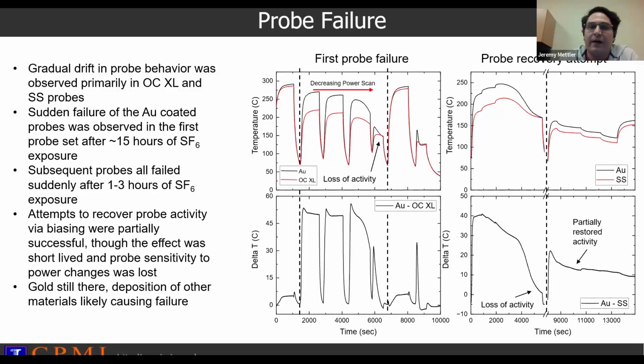Some bad news is that, unfortunately, the environment is quite punishing, and after some time, anywhere between 3 and 15 hours, depending on the probe, we were noticing that the probes were failing. They would suddenly, the temperature difference between them would start to collapse and then go to 0. And we suspect that that was due to deposition happening on the probe surface. And so we tried sputtering, applying a bias to remove that material from the surface. And while we were able to restore some activity, it wasn't a foolproof way to recover the probes.